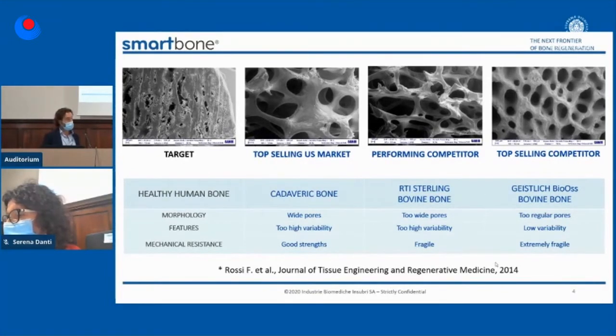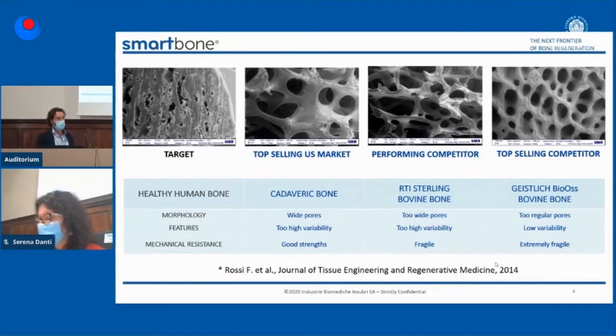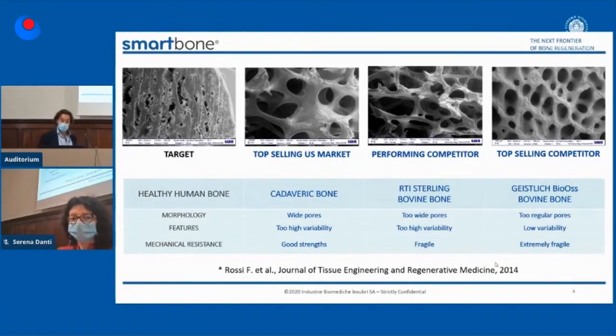The first one adopts a cleaning treatment at very high temperature. So they change the chemistry of the hydroxyapatite in order to reduce the volumetric resorption during the first days, the first week after the implantation. The other approach, the second product, uses a cleaning treatment with a chemical attack. This preserves the chemistry of hydroxyapatite, so it promotes remodeling, but obviously they have some problems in reducing volume immediately after surgery.